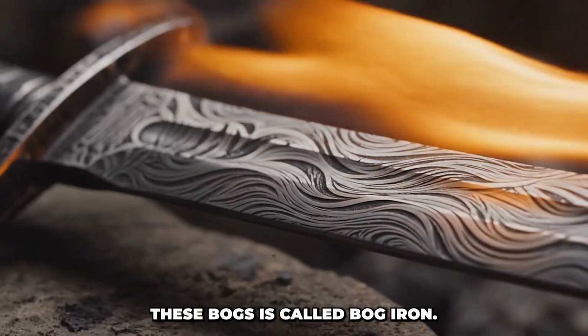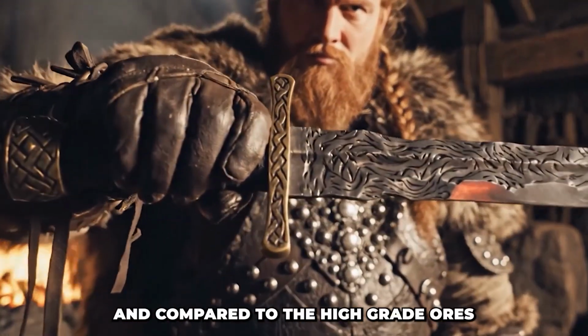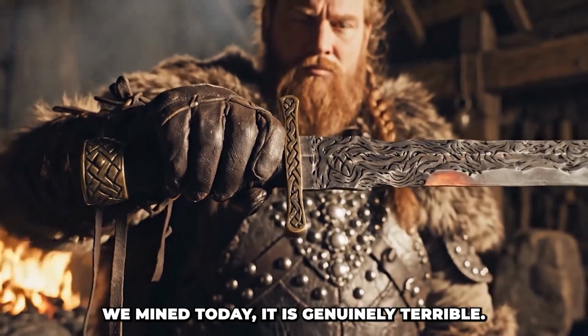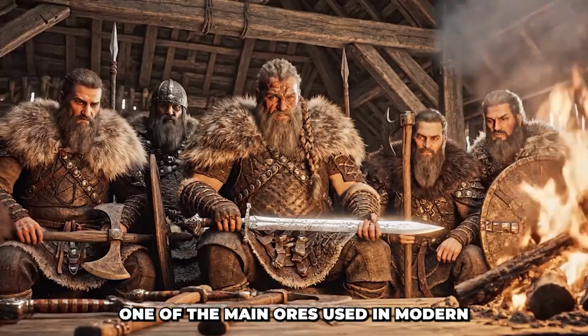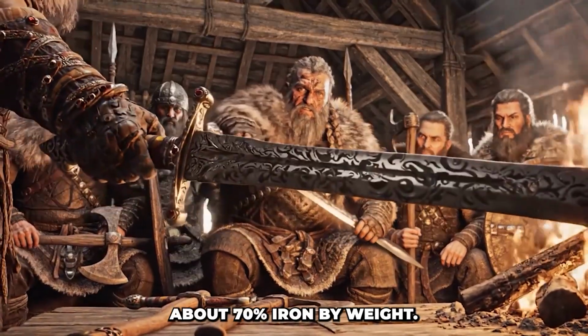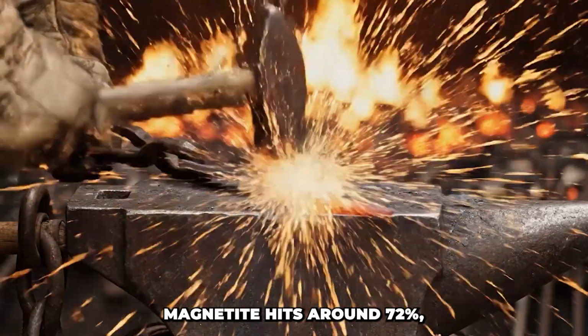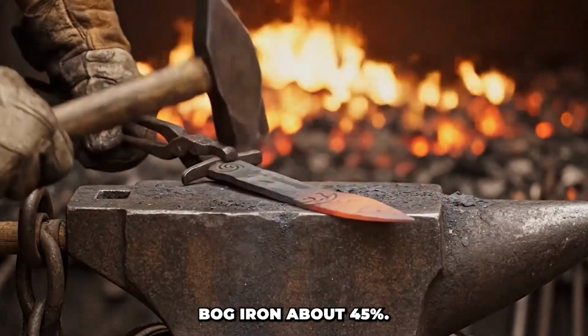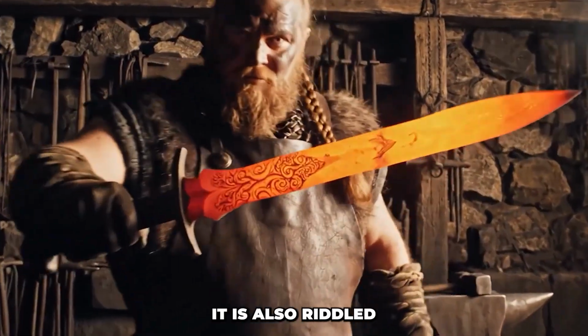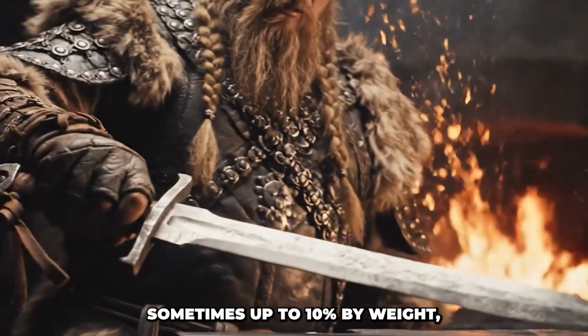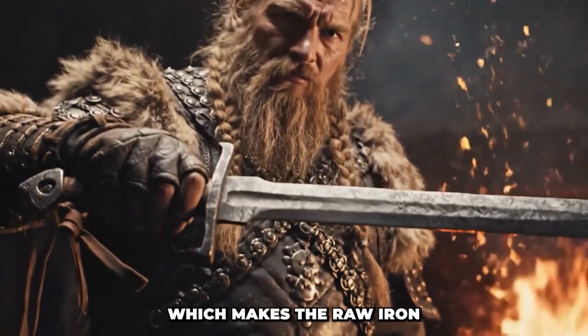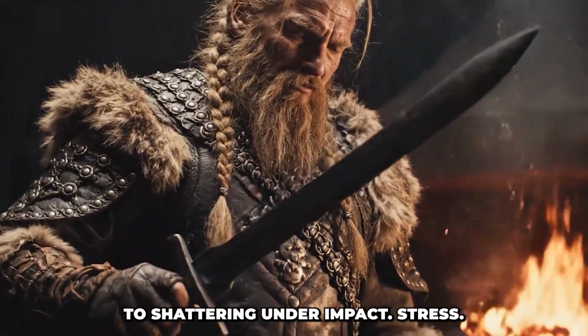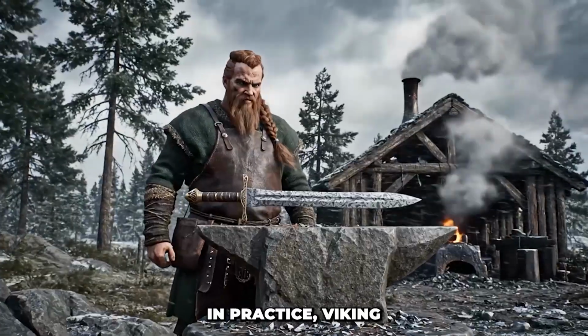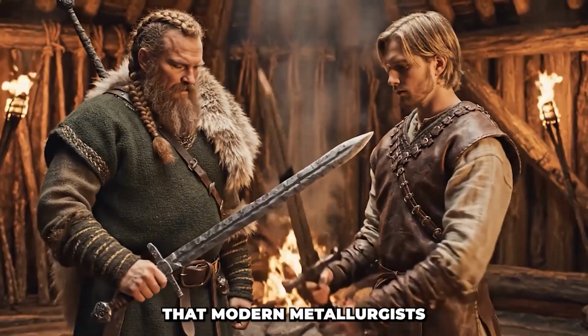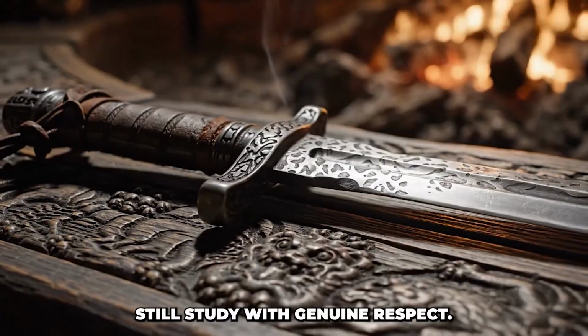The ore they harvested from these bogs is called bog iron. And compared to the high-grade ores we mine today, it is genuinely terrible. Hematite, one of the main ores used in modern steelmaking, runs about 70% iron by weight. Magnetite hits around 72%. Bog iron, about 45%. It is also riddled with phosphorus contamination, sometimes up to 10% by weight, which makes the raw iron cold, brittle, and prone to shattering under impact stress. On paper, bog iron is a bad starting material. In practice, Viking smiths figured out how to turn it into blades that modern metallurgists still study with genuine respect.